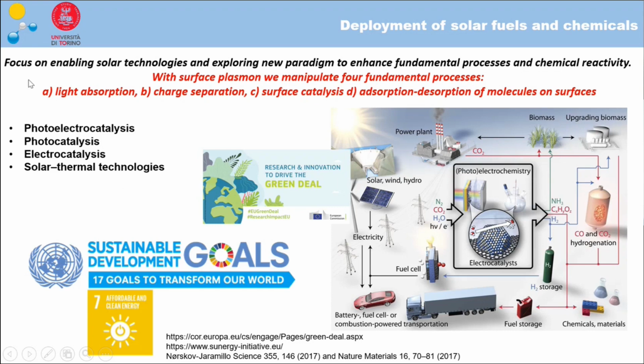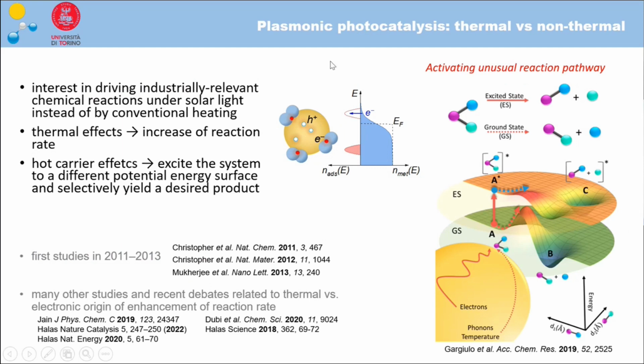And this is possible because, as we've seen before, with surface plasmons we can manipulate all the fundamental processes happening during catalysis or photocatalysis. So we can manipulate light absorption, charge separation, and lifetime of these charges. We can manipulate surface catalysis, so speed up some reactions or not. And also we can manipulate how molecules adsorb or desorb on the surface. So we can induce, for example, light-induced desorption of some molecules that sometimes poison the catalyst surface. So we can regenerate catalysts with this kind of materials. And in particular, I would like to discuss more about the possibilities that we can have with plasmonic materials.